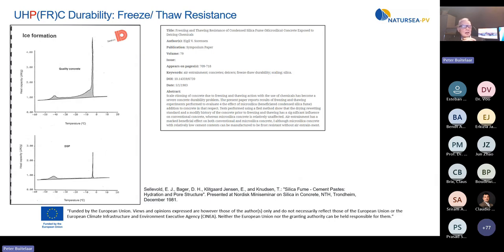Sellevold investigated in the early 1980s the frost resistance and ice formation at extremely low temperatures in UHPC and concluded that there is no ice formation taking place at ordinary freezing temperatures. We are talking about -50, even when the paste had undergone drying wetting cycles and is tested in saturated state. Thus, it is suggested that the microsilica containing DSP concrete could be made resistant to frost action without air entraining agent. Many other Scandinavian researchers, including my former colleague Eigil Sørensen, came to the same conclusion.